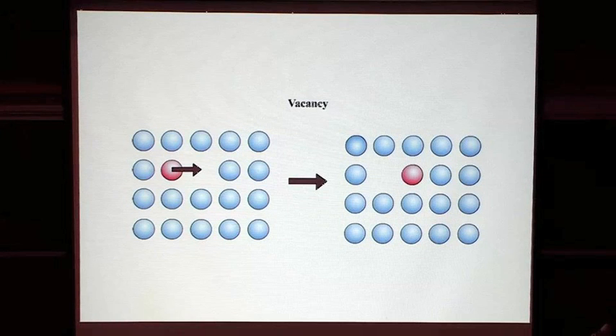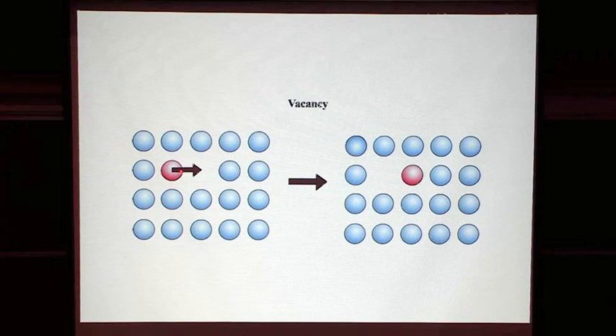So in fact, if we had an absolutely perfect lattice, diffusion would be very, very slow. The fact that we have vacancies allows this particular atom to move from one place to another. So the vacancies and the crystal defects are very, very important for pretty much all of the non-equilibrium properties of Earth materials. Maybe that isn't true for melts, but it's very true for minerals.